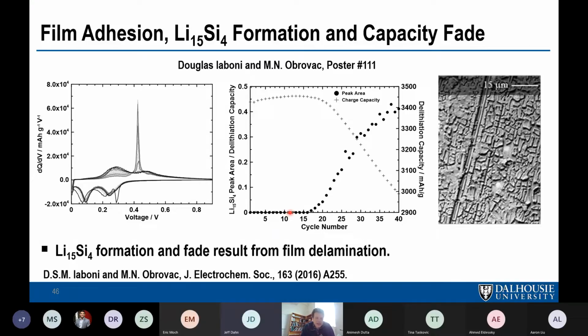But eventually you start getting these cracks forming, as you can see in the SEM image. In this SEM image, the edges of these flakes start to lift off. And if they're lifting off the foil, there's no more stress on them anymore by the foil, and so the voltage isn't shifted for these points in the alloy. And so you start getting some of the alloy forming 15-4. And of course, if these things are coming off the foil, that's exactly when you start getting electrical disconnection and fade. And indeed, the fade is exactly coincident with starting forming this 15-4 phase.